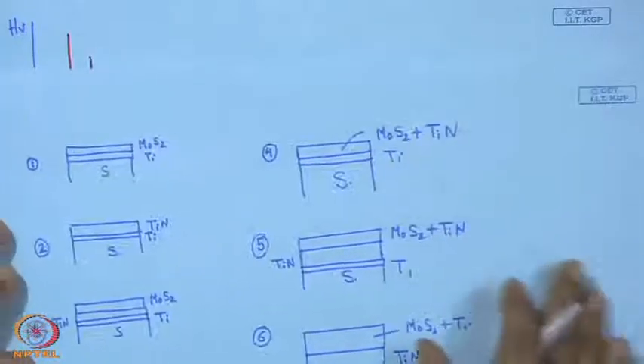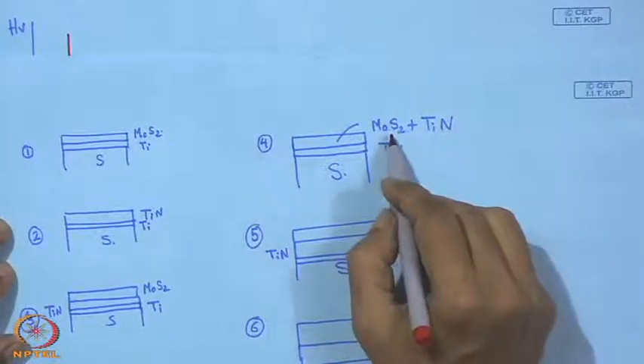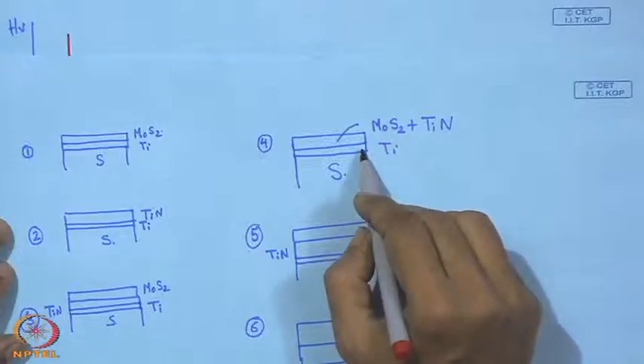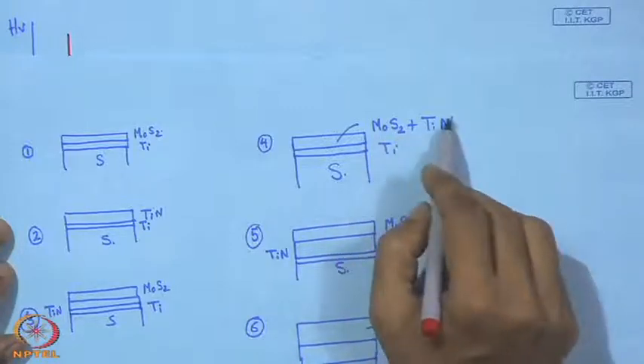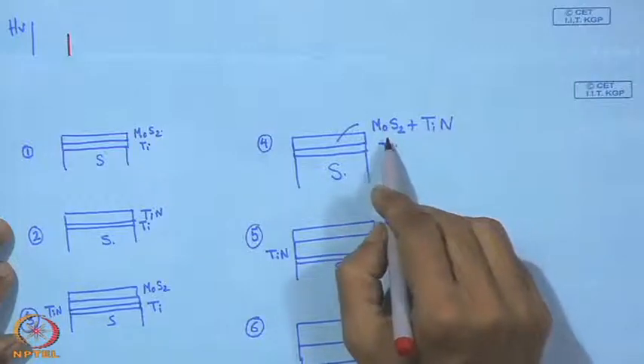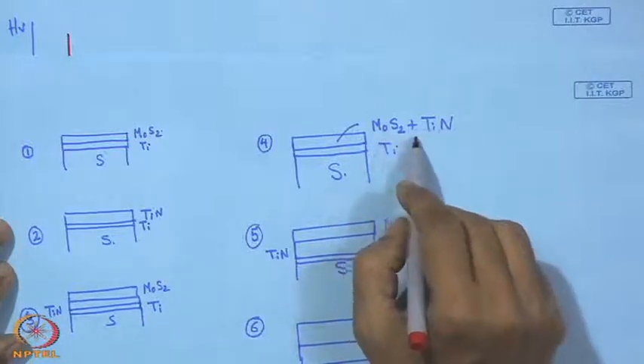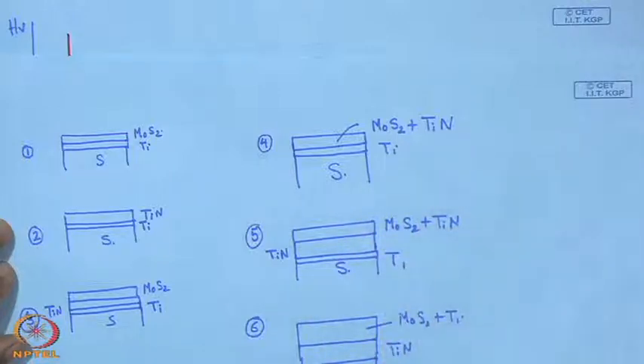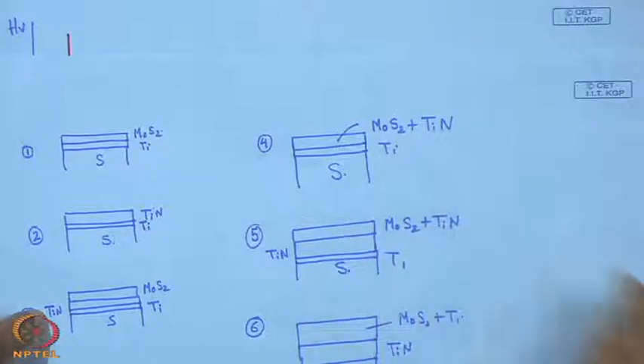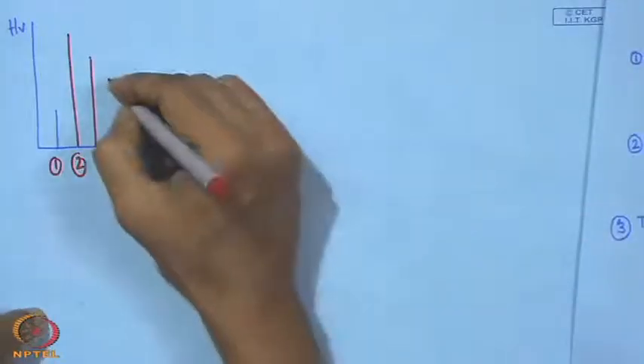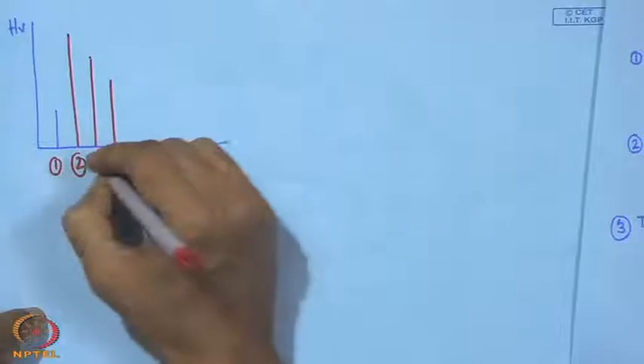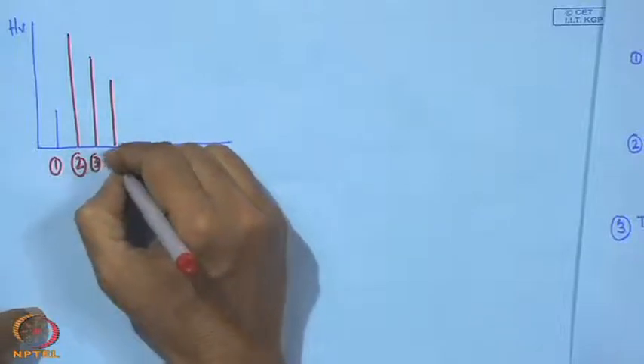And then we have number 4. In number 4 what we can see here is that it is a composite coating, but with no support layer of TiN. So, it will give a bulk value which will be more than MoS2, but it will be less than that of TiN. So, naturally when we see this value of TiN, then definitely this will be less than that one. So, we have something somewhere here, and this is going to be 3 and that is going to be 4.